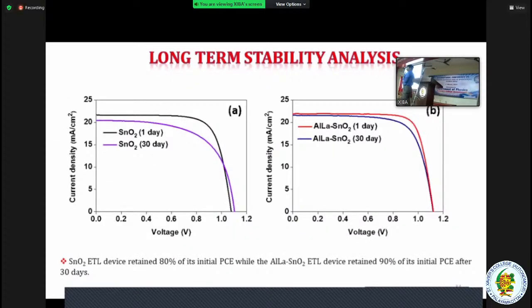The stability, as I already said, is a very important criterion as far as the perovskite solar cell is concerned. We kept our devices in the open atmosphere with a humidity of 40% for 30 days. After 30 days, the device retained 80% of its initial PCE in the case of tin oxide based ETL, whereas the aluminum lanthanum doped tin oxide retained 90% after 30 days. Even if you keep it at room temperature or with a humidity of 30%, that will be very safe. Next.